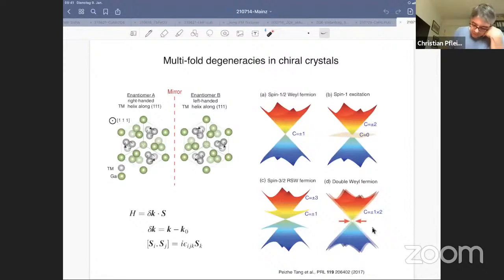One of the early works, and perhaps the starting point here for these multifold degeneracies in chiral magnets, was published in 2017. They were interested specifically in these compounds that I will be talking about, cobalt silicon and manganese silicon, because in the crystal structure they are lacking inversion symmetry, and the result is that there is a chirality in the crystal structure. So this is non-symmorphic, right? And they looked into the consequences of this non-symmorphic crystal symmetry in the electronic structure.